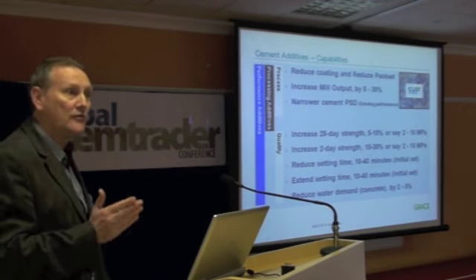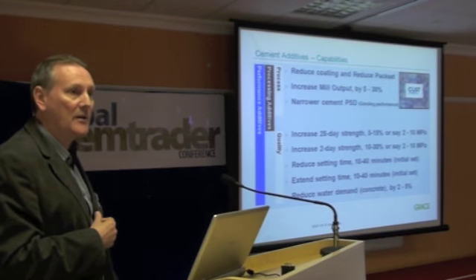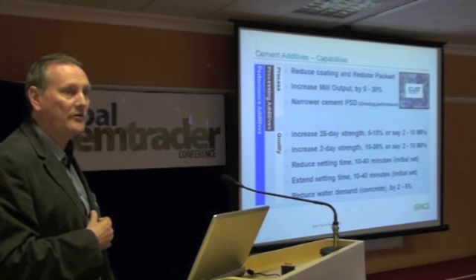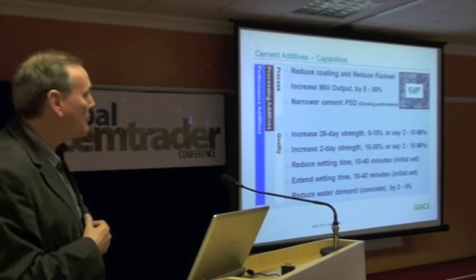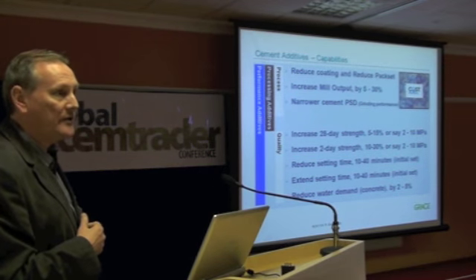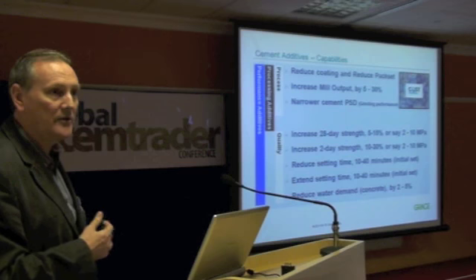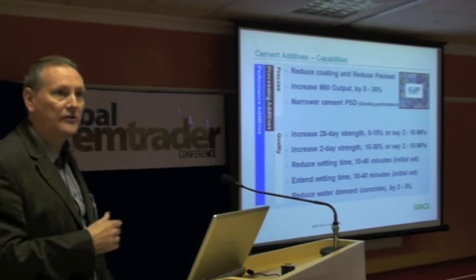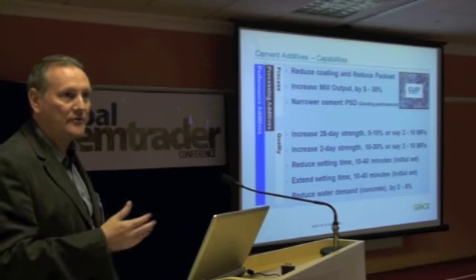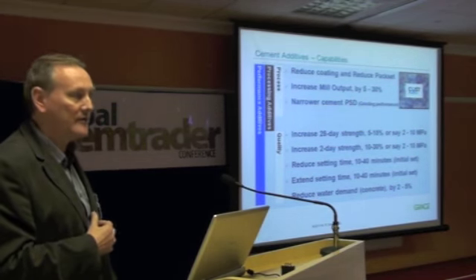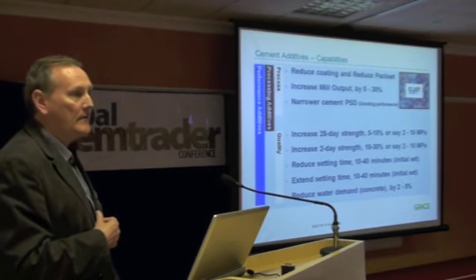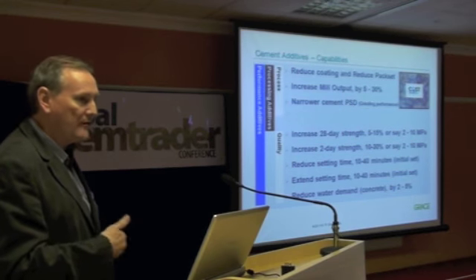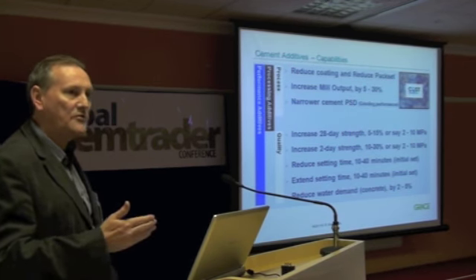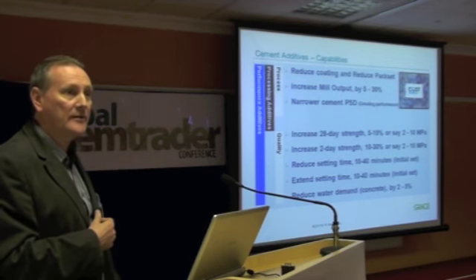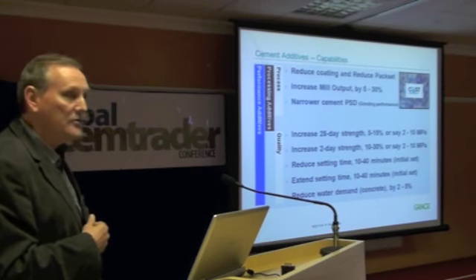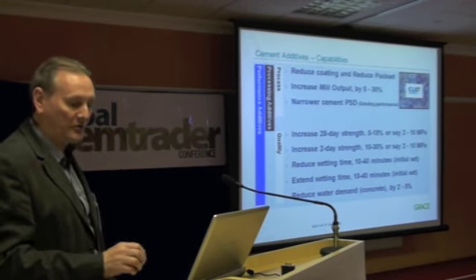Now 10's a lot. If you're talking 28-day strength of 50, 55 megapascals in a mortar, 10 megapascals more is quite significant. So that's the exception rather than the rule, but getting around 10% improvement at 28 days and up to 20% on the early ages is quite feasible. Same for setting time, not talking about trying to make 2 or 3 hours difference, but 10, 20, 30 minutes is quite significant. And also on the water demand, usually the cement producers are playing within the range of 2, 3, 4, 5% water reduction, as opposed to when similar chemistries apply to the concrete industry, where you have water reducers right up to the high range, super plasticizers, getting 20% or more.